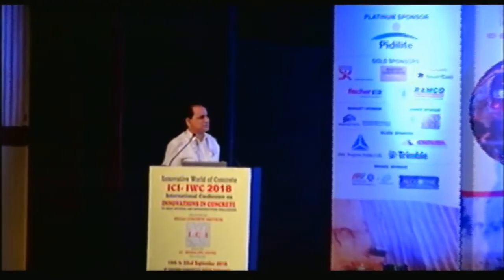Last Friday, around the same time, Vinod and I had the same discussion in Delhi. You can use any plasticizer, but keep water cement ratio 0.38. What he means is just to reduce cement, don't go into a high-end PCE based admixture. Am I right, sir? Right, sir. That would lead to more cracks than going with SNF, or a combination of SMF and mid PC. Water cement ratio is critical. Whatever be the kind of superplasticizer, it should not be less than 0.37 or 0.38.